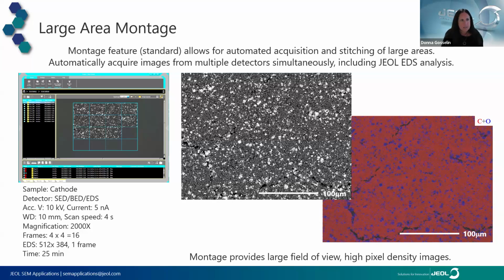So on the left here, we see our data management software. And in this example, I'm showing a 4x4 tiled frame montage. So we have a total of 16 frames. The whole montage was collected with both backscatter, secondary electron images, and X-ray intensity maps at each tile. And the entire process took about 25 minutes. On the right, I'm showing the composite image from those 16 tiles of the backscatter electron image, as well as an overlay of the carbon and oxygen maps.